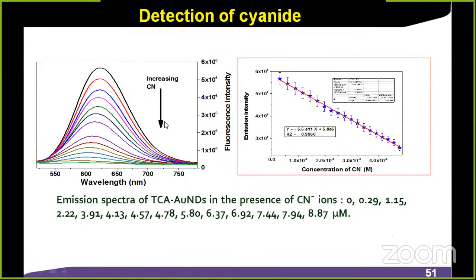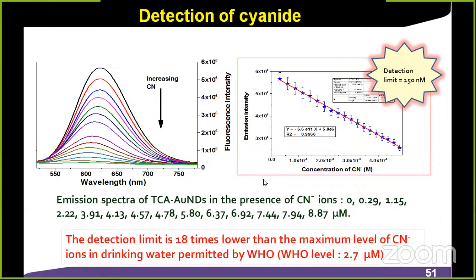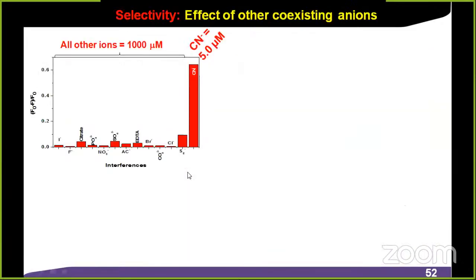And I applied it as a cyanide sensor. I added cyanide, then the peak fluorescence was quenched, and this is the intensity. Based on this, we calculated the detection limit to be 150 nanomolar. This is the lowest value among the reported papers. So ours is the lowest value, somewhat of a novelty. It is 18 times lower than the value recommended by the World Health Organization. They reported 2.7 micromolar, but ours we can detect 18 times lower.